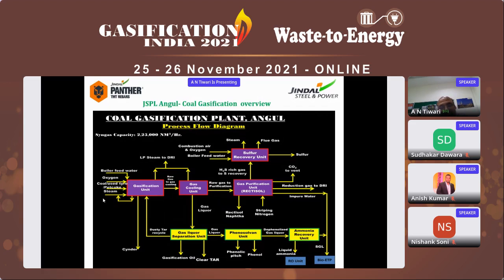The liquor stream goes to the gas liquor separation, where we have a gravitational separation. We separate tar and oil. Then the remaining liquor goes to phenolsolvent, where we mix with diisopropyl ether, and we extract the phenol. And then again we distill it to phenol and phenolic pitch. The remaining liquid goes to the ammonia recovery, where we recover the ammonia, and then it goes to the water treatment. Then we have an RO unit, and again the water is reused. So this is just about the brief of the JSPL.